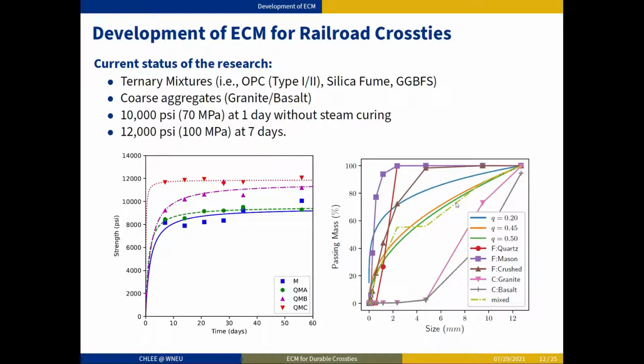One of the differences is that we use 40% paste content, which is slightly larger than the conventional concrete. However, as long as we get more information about aggregates, for example the surface area distribution, then we'll be able to get better control of paste layer thickness, which will give us room to reduce the paste content according to the designated purposes.